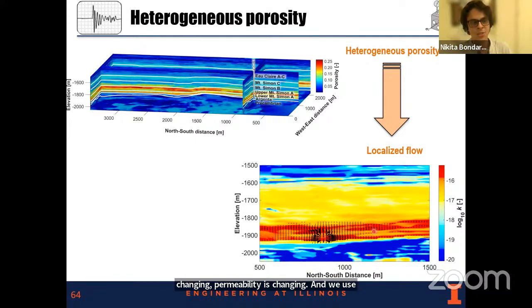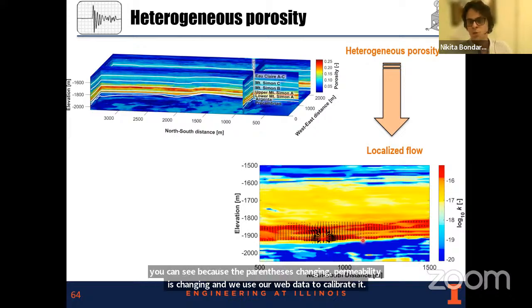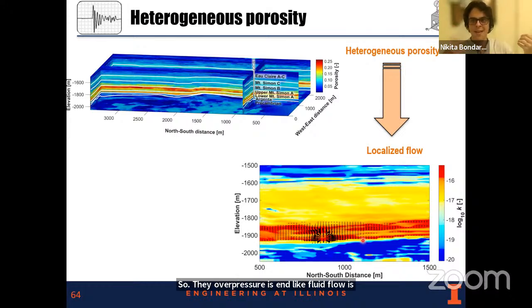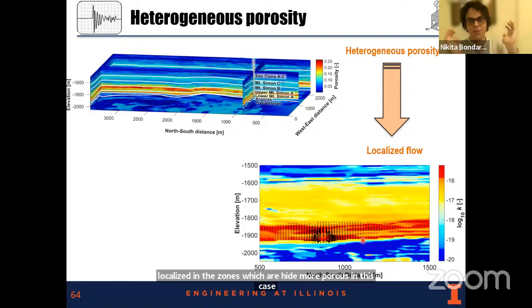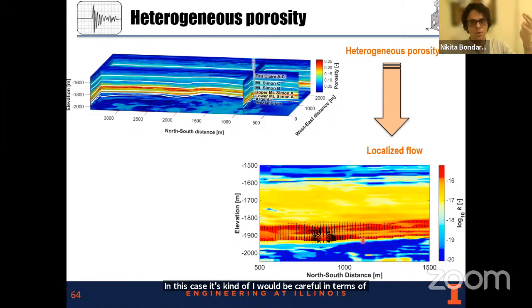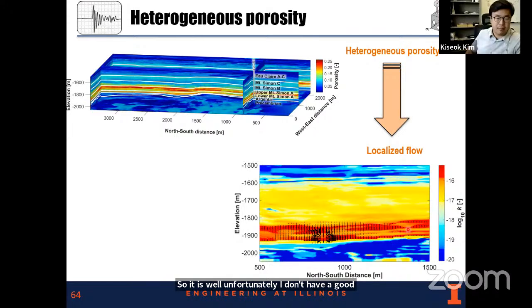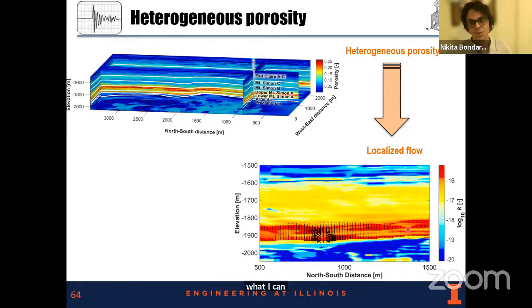So the overpressure and fluid flow is localized in the zones which are more porous. I would be careful about using very simplified numerical domains to predict the structure of the plume, because it affects the size of the plume - it will be localized in these high porosity zones. This is relatively usual for formations because they are heterogeneous, with different geologic histories. Unfortunately, I don't have a perfect answer - the only thing I can suggest is that we have to develop complex models. We cannot rely solely on machine learning to predict everything, because the problem is complex. We need complex solutions for that.